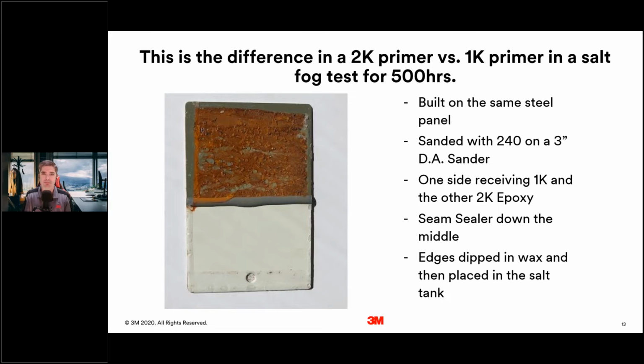And in order for any product to be truly corrosion resistant, and follow an ISO or ASTM certified test, you have to pass in a tank for 500 hours with no corrosion, meaning it goes in and it comes out and it looks like that bottom half of this coupon.